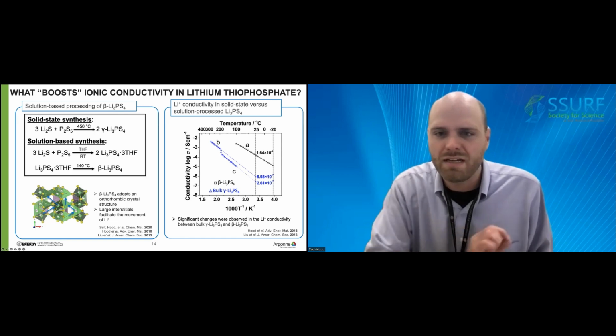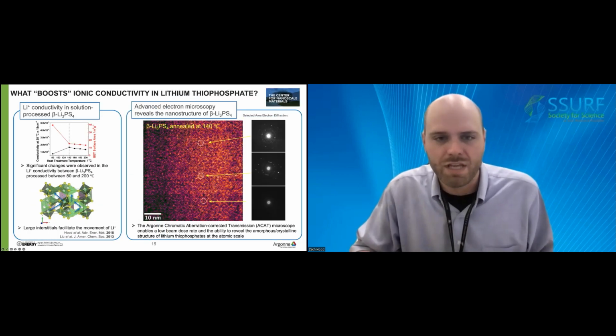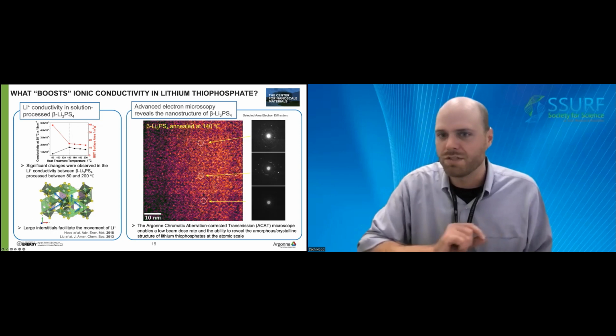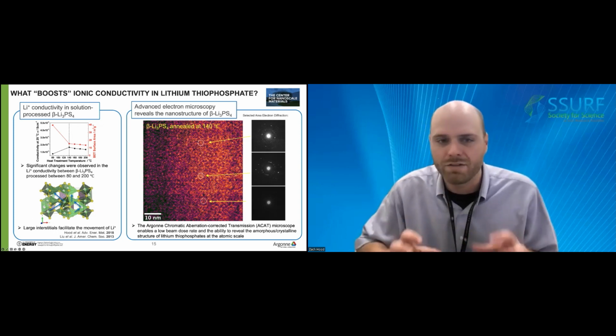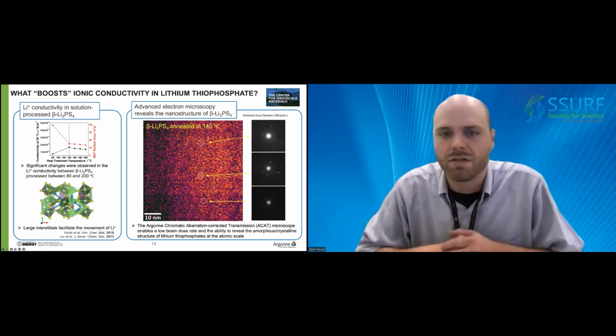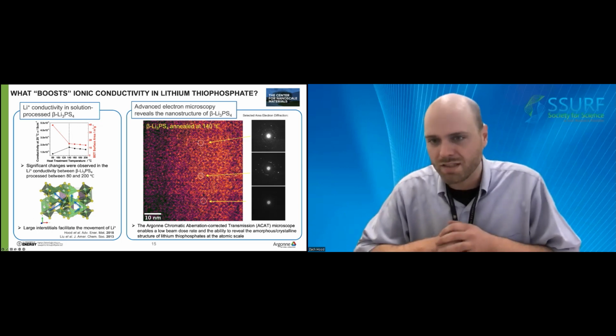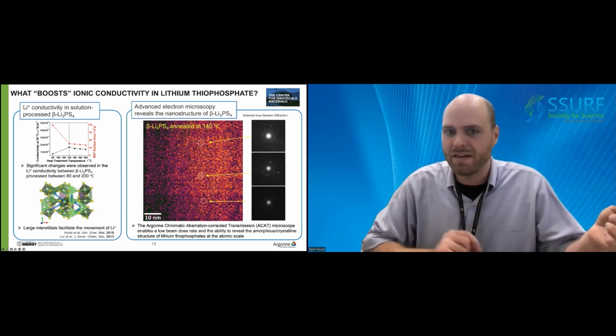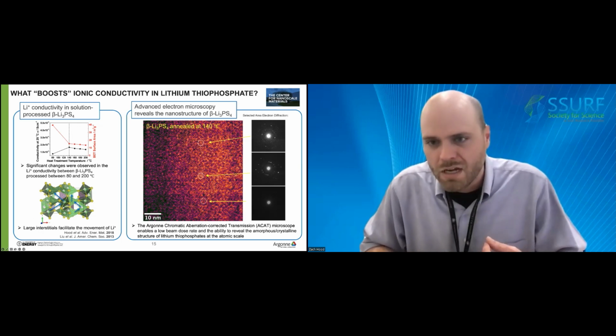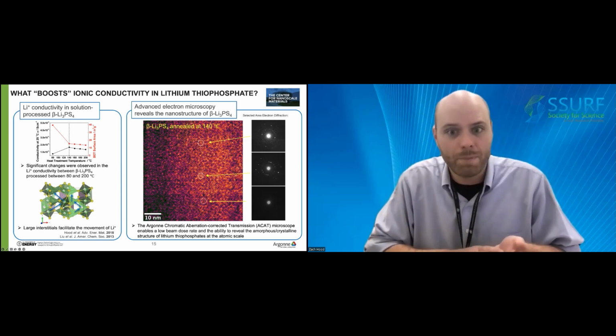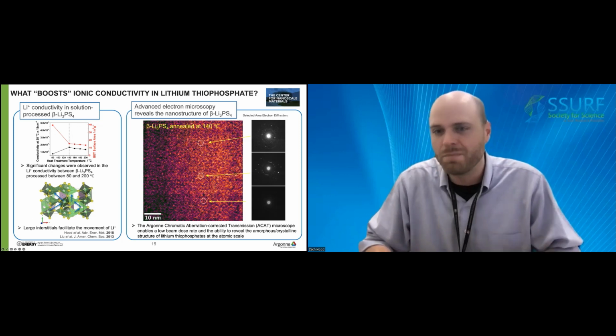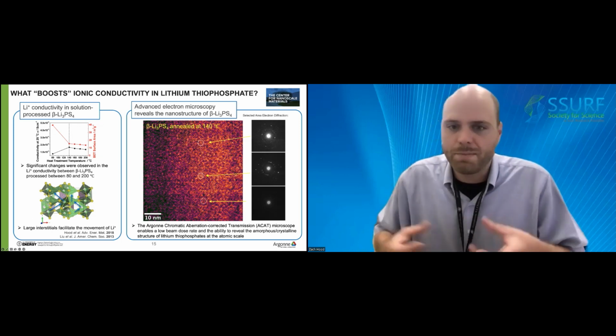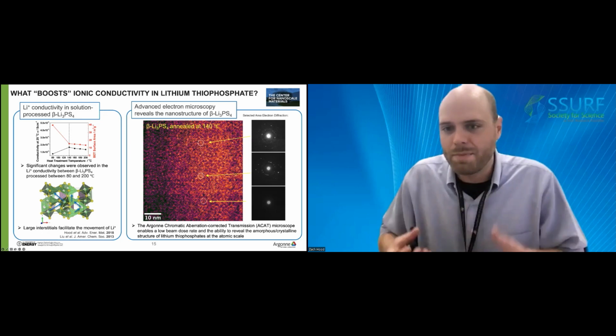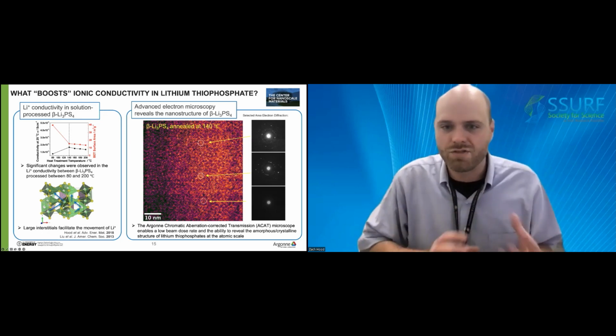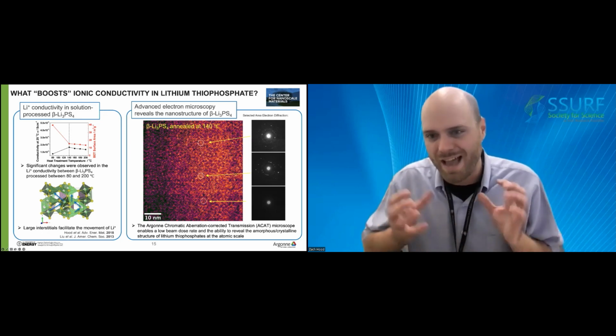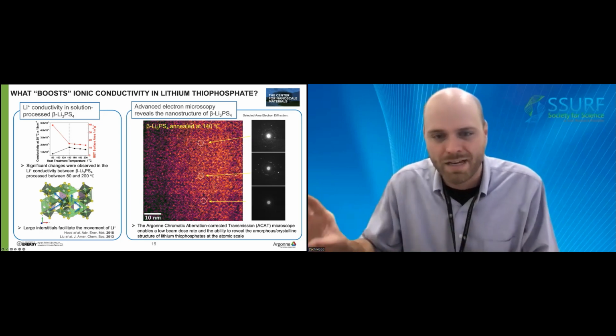So to get a deeper understanding of this material, we have developed and leveraged capabilities at the Center for Nanoscale Materials at Argonne National Laboratory in order to characterize films of the sulfide-based solid-state electrolytes. Traditionally, sulfides are electron beam sensitive, and at Argonne Center for Nanoscale Materials, we leverage the unique Argonne chromatic aberration-corrected transmission microscope known as ACAT. This microscope enables a low beam dose rate and the capability to reveal the amorphous and crystalline structures in lithium thiophosphates at the atomic scale, as shown on the right-hand side of this slide.